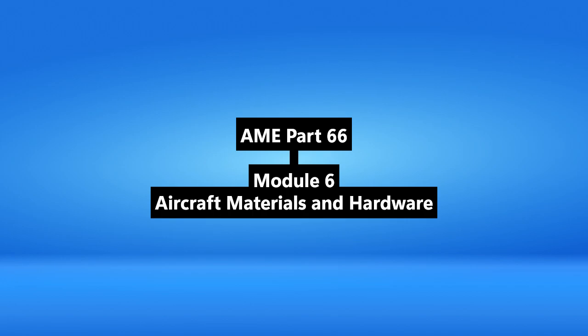What other non-ferrous players are big in aircraft materials? Magnesium's really interesting. It's the lightest structural metal out there, about 2/3 of the weight of aluminum. Wow. Alloyed with zinc and aluminum, it gives an incredible strength-to-weight ratio, good for secondary structures where weight is critical. And titanium. Titanium looks a bit like stainless steel. It has a unique spark test, a brilliant white burst, and it'll leave a dark line if you draw it on glass. Why is that? Formation of titanium oxide.